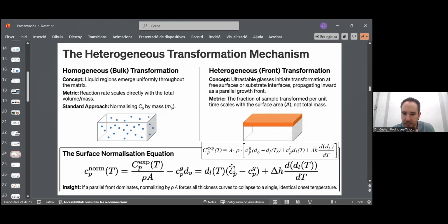And then when we do this, what we can do to normalize this is to keep in one side of the equation all the parameters which do not depend on the particular sample we are measuring. Which means the thickness of this liquid layer, which does not depend on the thickness of the sample, which is only a property of the temperature, and these parameters which are properties of the material: the specific heat of the liquid, the specific heat of the glass, and the enthalpy of transformation.